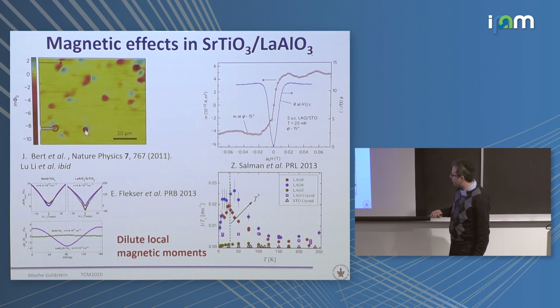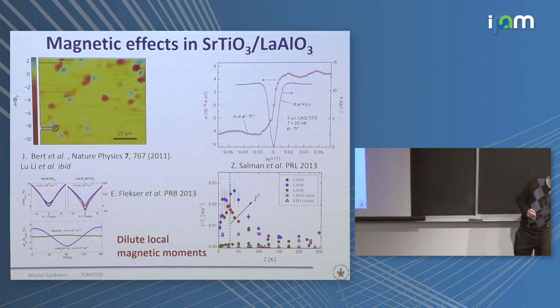So it's not yet so clear what they are, but it appears that there is some local magnetism, although because it's local, when you do 2D transport, it doesn't affect you so much. For example, you see an isotropic magnetoresistance, but you don't see any hysteresis. You start seeing those things when you go to those 1D systems that I mentioned, and then it's clear that even if along the 1D there is just one magnetic region like that, you will be sensitive to it, but somehow in 2D you are less sensitive to it. So I'm going to forget about magnetism in the following.